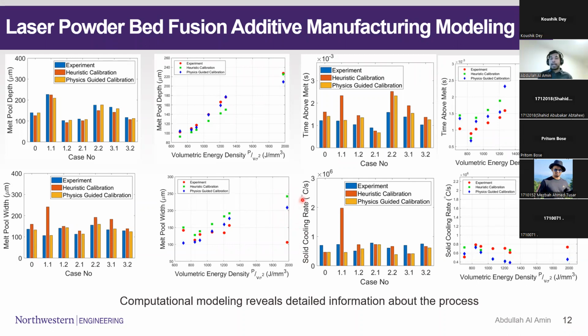In addition, there are the other two measurements that NIST asked the modelers to submit. The first is the time above melting, meaning how long a particular scan track has been in the liquid region. I compared them with the two different methods. Again, in a similar fashion, I compared them with the volumetric energy density to see if there is a linear, nonlinear, or other mathematical relation that I can come up with. In a similar fashion, for the solid cooling rate, the red method is giving us some error, but that improves, or mitigates the deficiencies, if I use the novel techniques that I introduced.